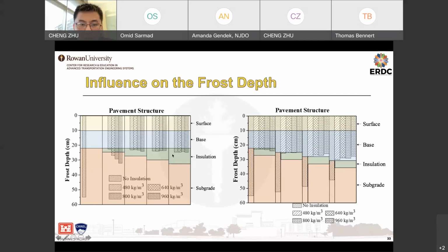However, for the insulation layer, we can also see that the effect of thickness on further reducing the frost depth is not that clear. On the other hand, we also tested the depth of the insulation layer. As you can see, if we move the insulation layer to a deeper depth, the frost depth also gradually increases, and this actually meets our expectation as well. So overall, you can see the influence comes from the thickness and the position of the insulation layer. Both of these should be taken into account during the design.